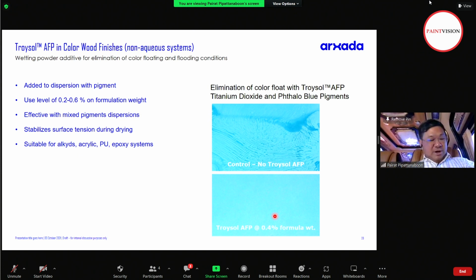So you need to make sure that your paint after tinting doesn't have color float and color flattening because of too much surface tension in the system, too low thixotropy, or coarser pigment or fillers, when you change your raw material of pigment and filler extenders. The particle size becomes coarser, the application of the paint becomes thicker layers, and the evaporation rate of the solvent is too fast. So these are the factors involved with the color float, color flux problem.